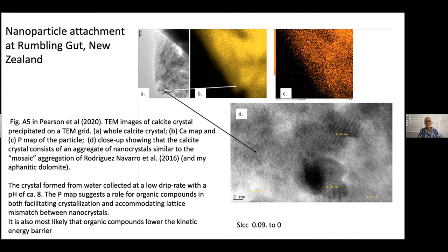Then at the TEM, you have an EDS, so you can also look at the composition. And what was striking is that you have a lot of phosphorus. So I don't know, maybe phosphorus is related to organic compounds. So it's there, and it might be that the organic compounds, again, are helping the nanocrystals with the mismatch of the lattice. They are bridging it because there is a slight lattice mismatch. But again,